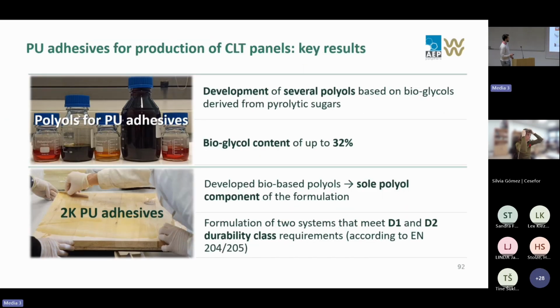I'm just going to summarize quickly some of the results that we obtained related to the polyurethane adhesives. We managed to develop several polyols based on the bioglycols derived from pyrolytic sugars with a bioglycol content of up to 32%, which was one of the targets of our work. We then employed these polyols as the sole components in the polyol part of the adhesive formulation.